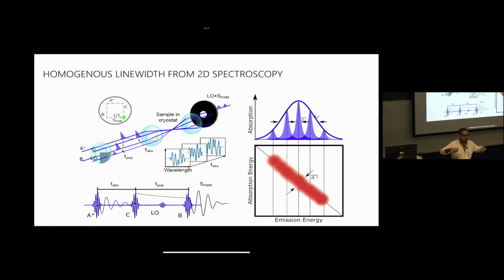Maxwell tells you you've got a time varying polarization with a non-zero second derivative. This should emit. You have emission, you detect it here, and you measure the amplitude and phase of that. And that's one energy axis, right? But now you also scan the delay between your first two pulses, which is a coherent response, which is in the time domain, your electronic spectrum as well.